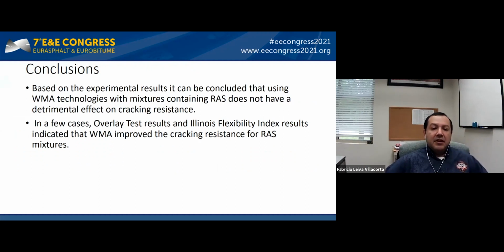So in conclusion, we were satisfied with the results. We didn't observe any detrimental effects on cracking resistance based on those five different tests that we conducted. And that was part of what we were looking for when we started this study, because the concern was that the warm mix technologies were going to lower the temperature during production, and that may reduce activation of the asphalt that is part of the asphalt shingles. And we were able to observe that was not the case.